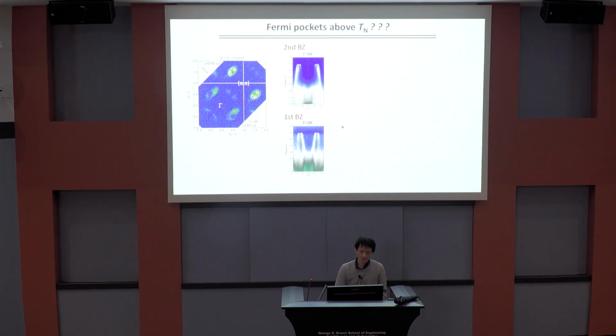So maybe people wonder what happened at a high temperature above the Neel temperature, which was estimated around 135 Kelvin from NMR. And the quality of dispersion is very sensitive to the different Brillouin zone due to the matrix element. For the first zone, you can clearly see the back-bending of the band dispersion.